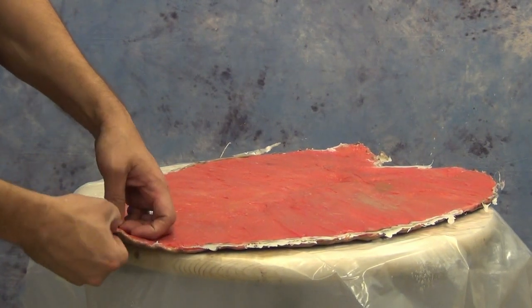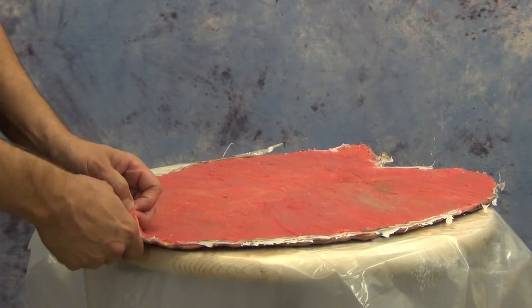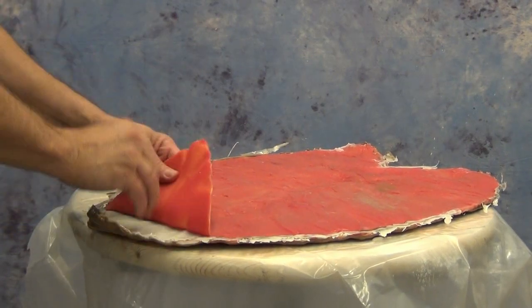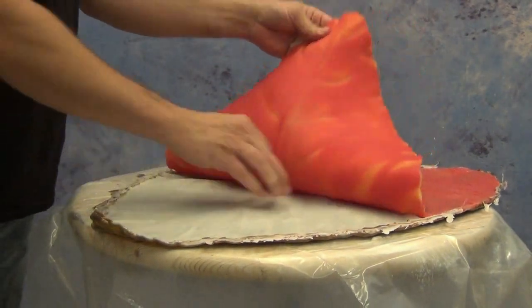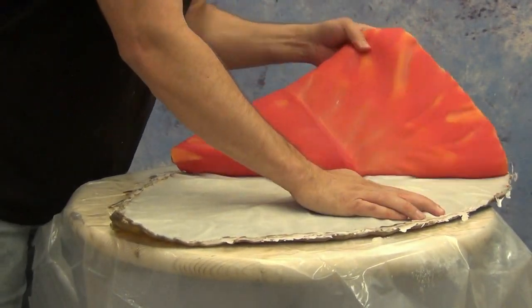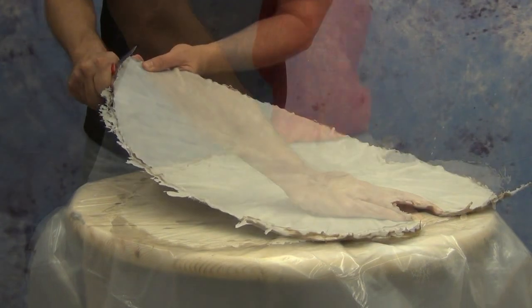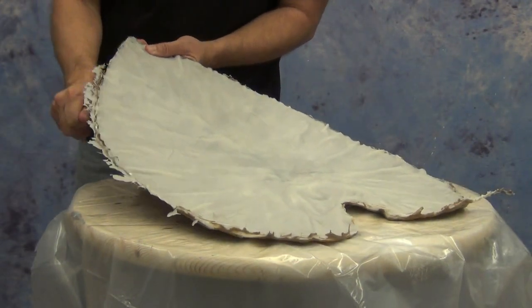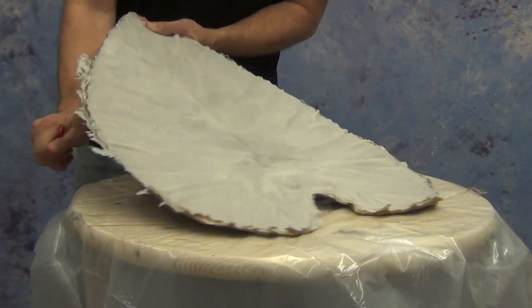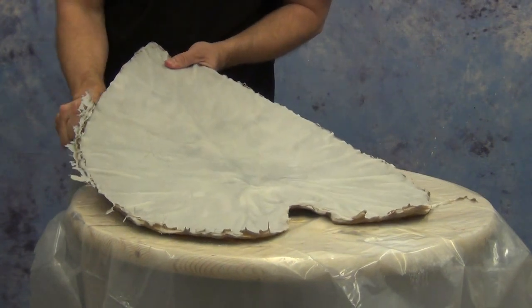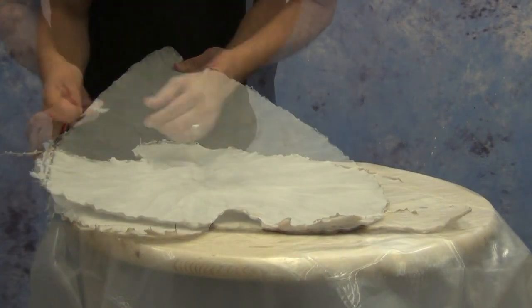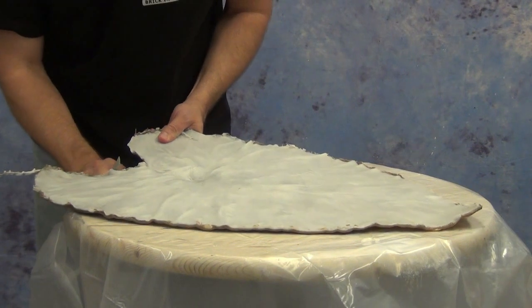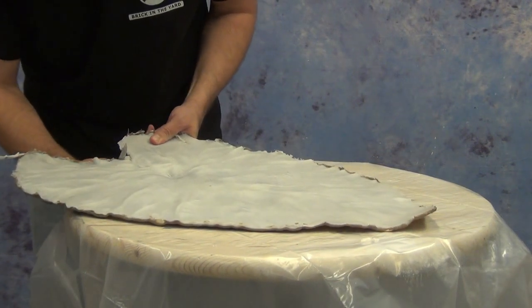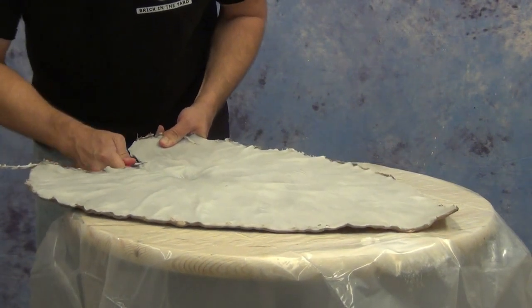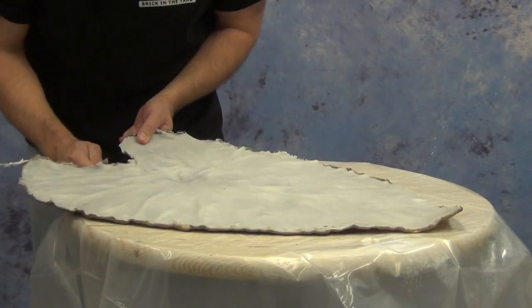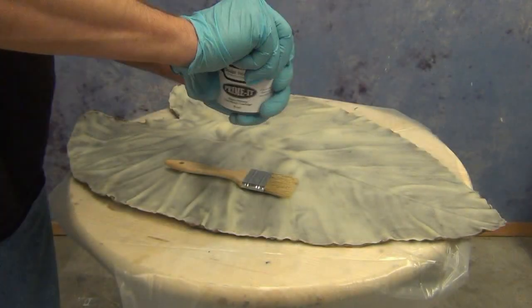And I'm actually demolding this a little bit early. You notice that this cast is still a little bit flexible, and that's okay. For this particular cast, we actually want that because at that stage, if we need to, we can warp this leaf to give it some extra contours that it doesn't have right now in the mold. But more importantly, at this stage, it's very easy to trim. So we can come back with a craft knife or even scissors and trim back that edge. And once we've trimmed that back, ready, let it cure completely and apply our primer.